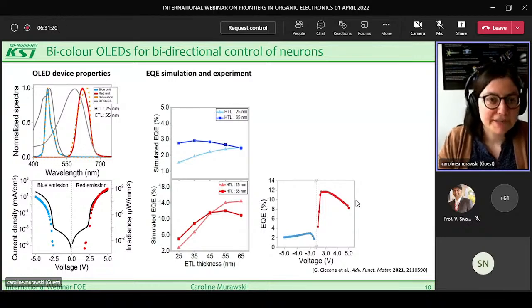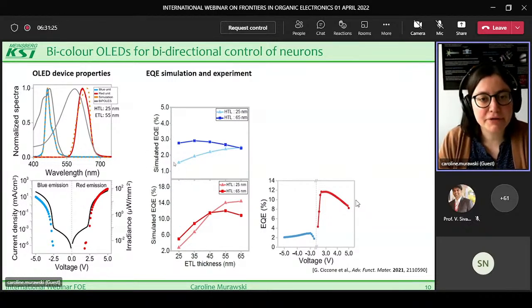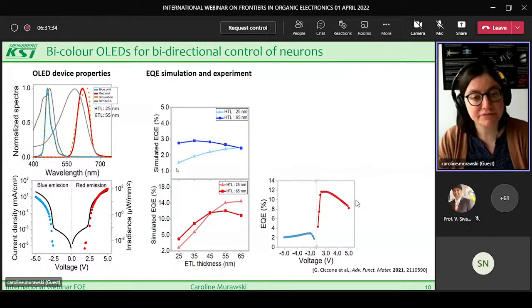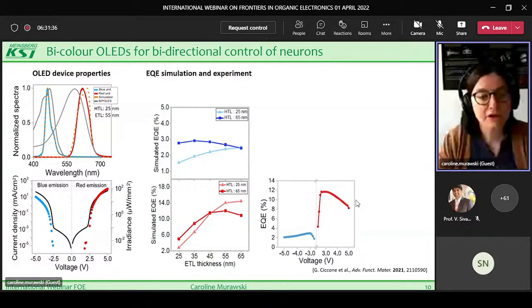We also studied the external quantum efficiency, both in simulation and in experiment, and this is shown here. So again, for different thickness of the electron transport layer, we also vary the external quantum efficiency, of course, because we can have higher or lower outcoupling efficiency. This is particularly visible here in the red stack, where we can change the external quantum efficiency between around 3 and 14%, depending just on the thickness of the electron transport layer.